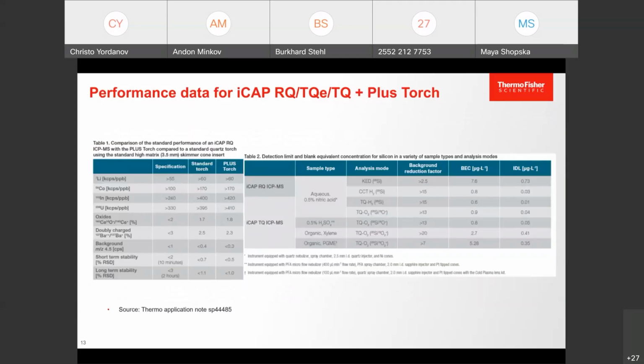The tricky point is, it was not only a better background; a lower background automatically means higher sensitivity. It was valid for the whole elemental table. So with our new Plus torch, we could say in our warranty specification, they are much higher than the specification that we run in practice with a normal glass torch. So our sensitivity is higher.